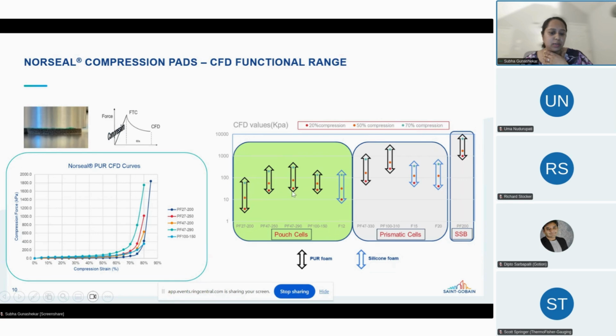The same way, some pouch cells or prismatic cells are much more rigid and they need more pressure. So in that case, we have our products with a higher density, which can provide your initial beginning of life pressure value close to, let's say, 100 kPa, and then go up to 1,000 kPa. Whereas in solid state batteries, we're seeing that the pressure requirements are much higher. It starts at about 1 megapascal, but within 1 to 4 megapascal, we want a flat curve. So this is where the customization comes in handy.